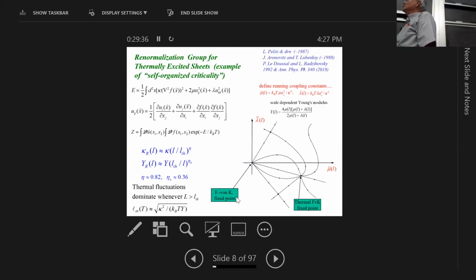And it turns out, as pointed out to me by Paul McEuen, if you put in numbers for room temperature graphene with its appropriate Young's modulus and its appropriate bending rigidity, this length is about 0.3 nanometers. So at room temperature, if you're larger than that, pretty small length, 3 angstroms, you better pay attention to these running coupling constants. Nice question.